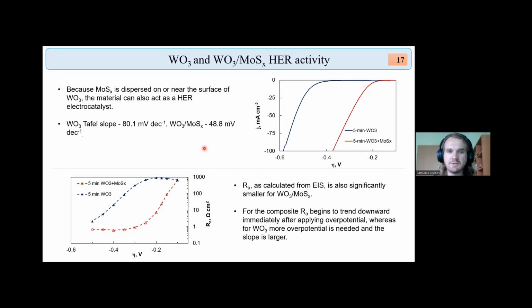And finally, very briefly, I will mention that these composites, because they contain molybdenum sulfide, can also act as hydrogen evolution electrocatalysts. Shown here are two polarization curves, one obtained for a tungsten oxide sample, which reaches about 100 milliamps per square centimeter at 0.6 volts applied overpotential, whereas the composite has much lower potential values because there is electrocatalytically active molybdenum sulfide on the surface. And again, we apply the same electrochemical impedance spectroscopy analysis by modeling and calculating adsorption resistance values, and we obtain, not unexpectedly, results that the adsorption resistance is much smaller for these samples that contain molybdenum sulfide and are thus electrocatalysts.